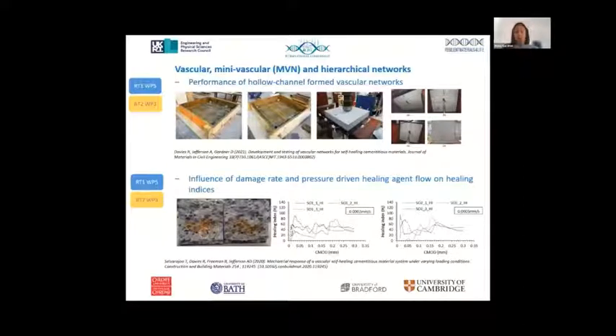We've spent, as have Cambridge University, quite a lot of time developing one-dimensional, two-dimensional, three-dimensional networks that we can create via printed polymer elements, whether we leave them in situ or whether we remove them. But we've had quite good success from being able to load these vascular networks with our healing cargos. We've been able to flush them out. We've been able to damage and get some healing and also to recharge these systems again. So we're really looking now, when we're thinking about vascular networks, about the next stage, about creating these at larger scale, though we have had some good success at our medium size scale up in terms of our slabs and some of our wall elements.